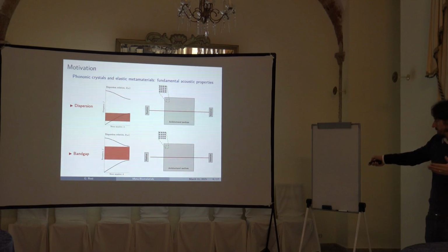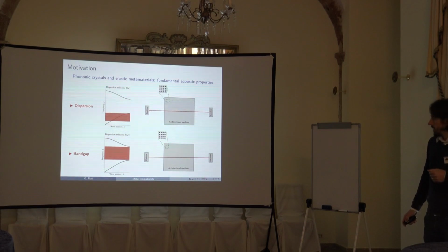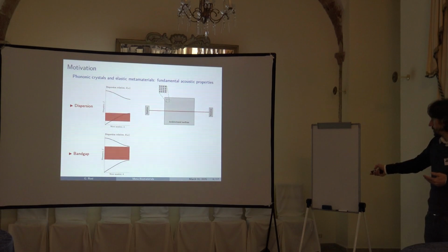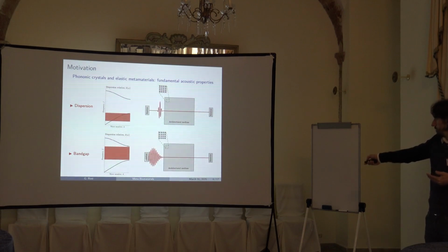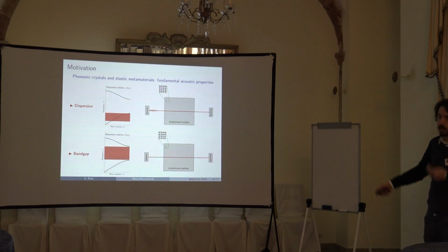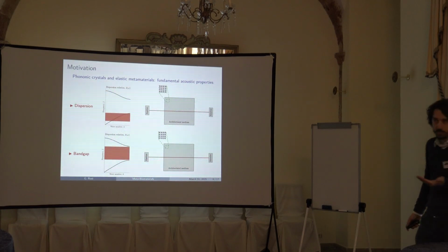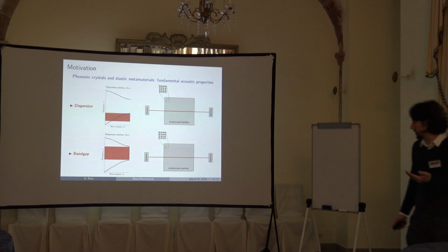It is completely reflected. Usually this kind of feature is widely used to damp, or let's say to optimize the fact that the receiver, you can see, is not receiving anything. We will use it in another way. We will exploit the fact that you have a big reflection when you enter the bandgap. Okay? So much bigger than the reflection you have when you are outside the bandgap.